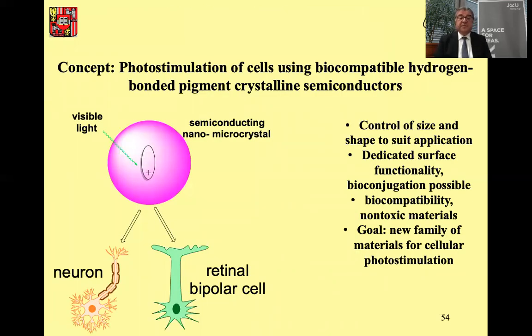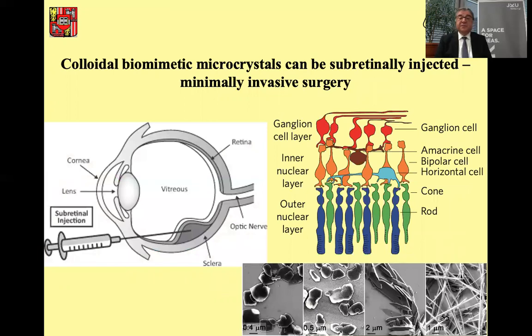But if you have a possibility to open and close the ion channels, of course, we can immediately think of retinal bipolar cells in the human eye, because these cells are also opening and closing ion channels upon light stimulation, photostimulation. And if we could do this with our artificial systems, then this would be an artificial retina. Can we do that? Yes, in principle, it should be possible to have these microcrystals, nanocrystals put behind the retina, and then the ganglion cells and the bipolar cells grow on these artificial absorbers, and then the ion channels can be opened, even colored vision possible.